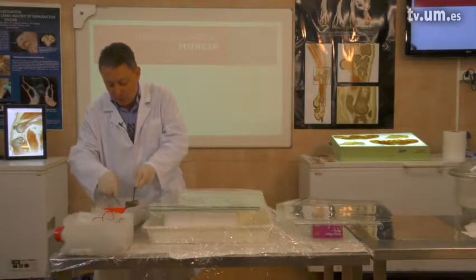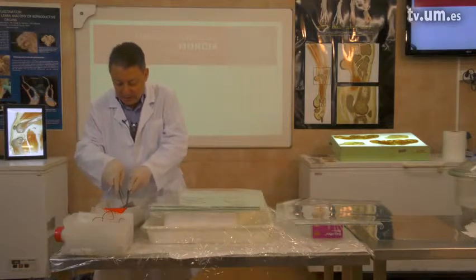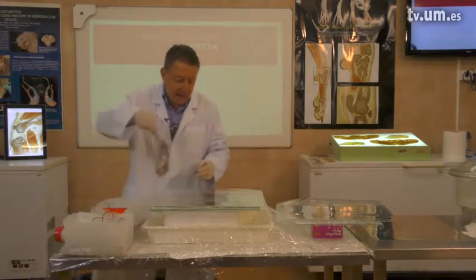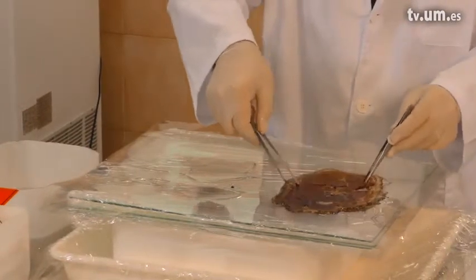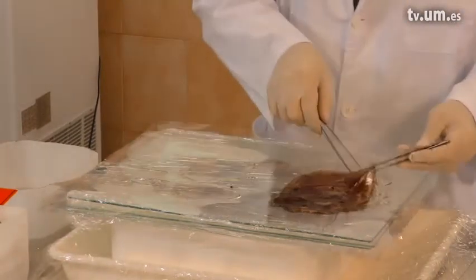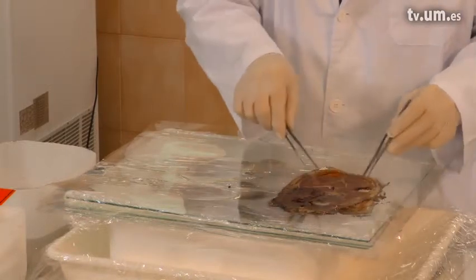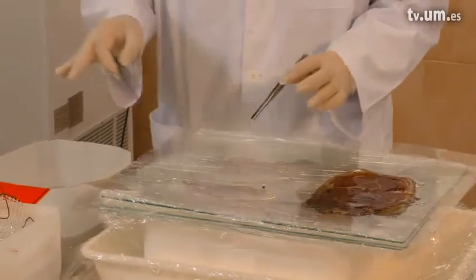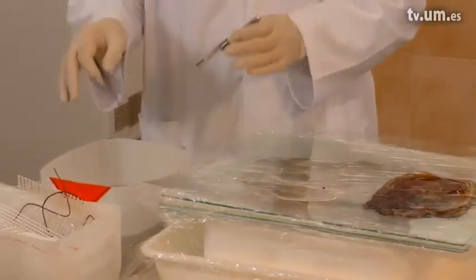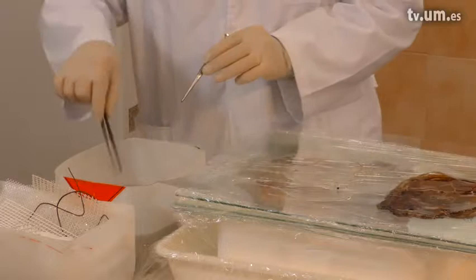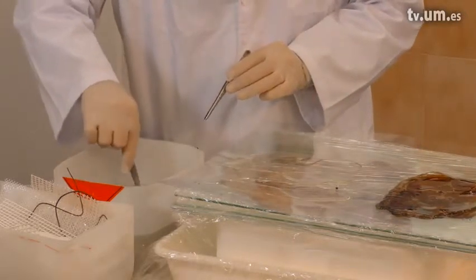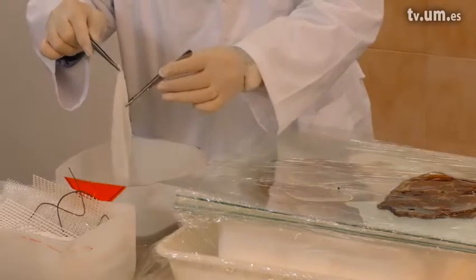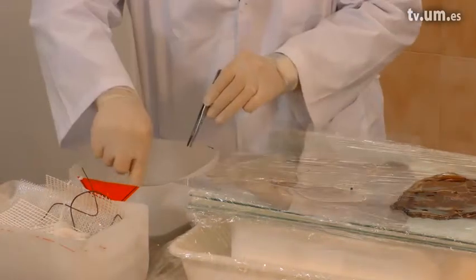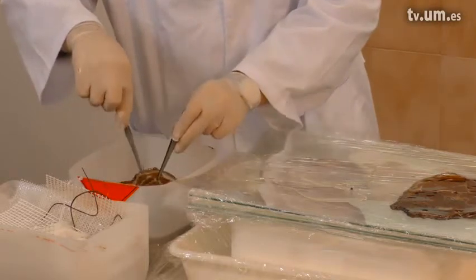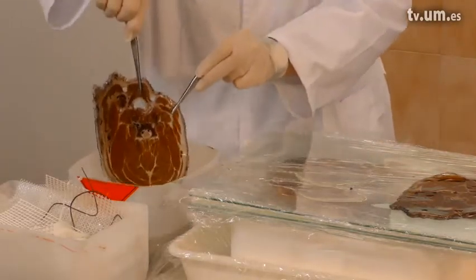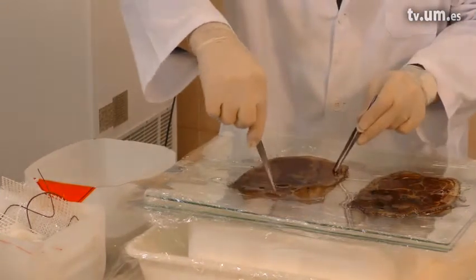Essential, when you do this procedure, is to keep the slices out of the resin as short as possible, draining the resin out of them. If you keep them only a few seconds out of resin, nothing happens. But if you drain them too long, air could go into the slices, between the structures of the slices, and you will have trapped air bubbles. So the main idea is to keep the draining stage of your slices very short.